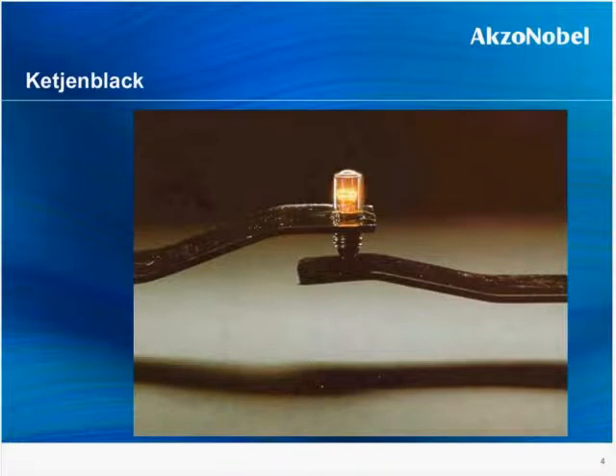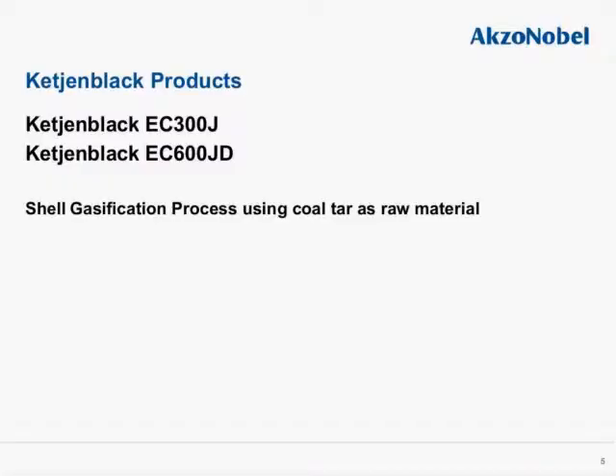Okay, going back to Ketjenblack, the superconductive carbon black that can turn an otherwise insulating plastic into a conductive product, as shown in this picture, which can actually conduct electricity. So in this line of product of Ketjenblack, we have two grades: Ketjenblack EC-300J and Ketjenblack EC-600JD. Both these products are made by a process called gasification, and we control the product's purity by using an extraordinarily pure raw material, which is coal tar, and this is the raw material from which Ketjenblack products are made.